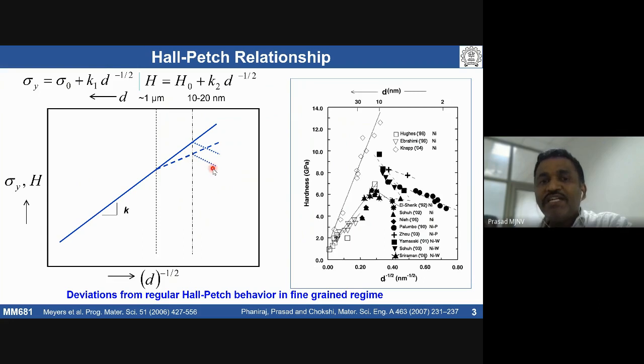Inverse Hall-Petch basically means stress is inversely proportional to grain size. Finer the grain size, higher the stress according to regular Hall-Petch behavior. In case of inverse Hall-Petch behavior, sigma y is directly proportional to d to the power of some slope. That means a grain boundary weakening mechanism contributes to this inverse Hall-Petch behavior in fine grained materials. This has been well established in various materials. This is a summary plot which basically summarizes some of the data findings on nickel based materials where people have reported presence of inverse Hall-Petch behavior.